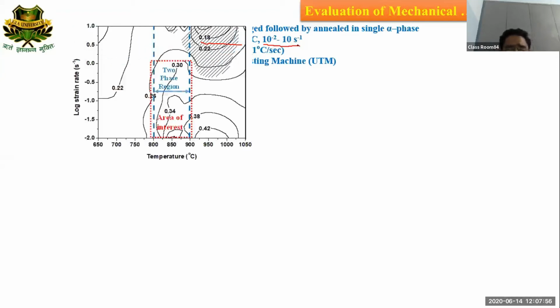With the data which we obtained from this thermomechanical simulator, we have developed this kind of processing map for this particular alloy. Here you can see the data is from 650 to 1050, and as I told you in the previous slide, around 800 to 900, give or take 10 to 20 degrees, there is a domain known as the two-phase domain, with a mixture of alpha phase and beta phase. That means a mixture of HCP crystal structure and BCC crystal structure. So I am totally focusing on the two-phase domain.